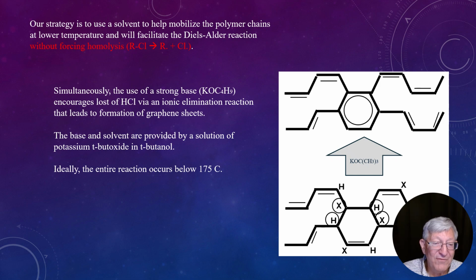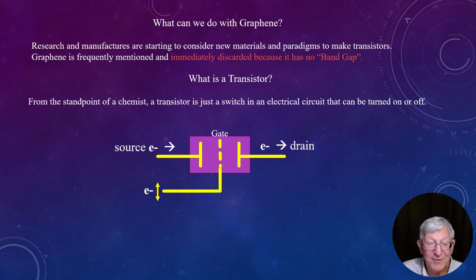And so we believe that by keeping the whole reaction temperature below 175 degrees, we can cause the polymer to go to a graphenic approach as opposed to this random jumble of free radical combinations. Those are the hydrogens that would be plucked off by the base.